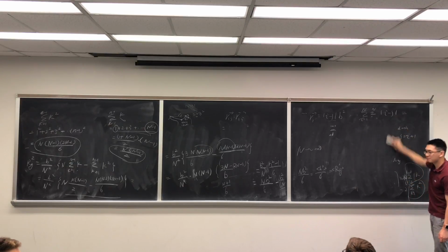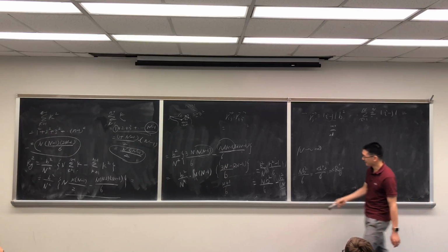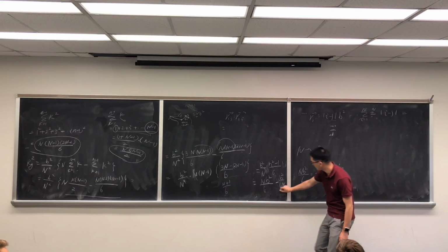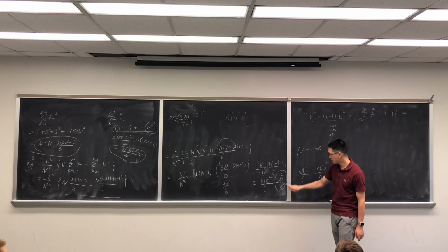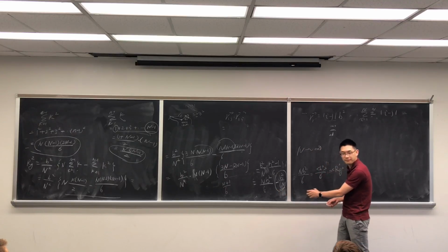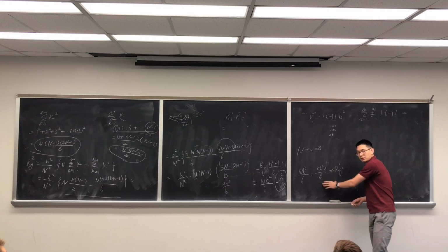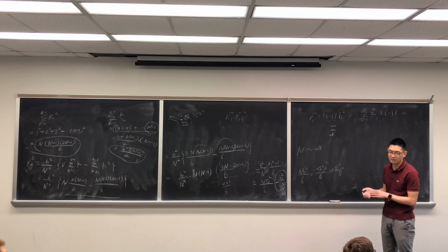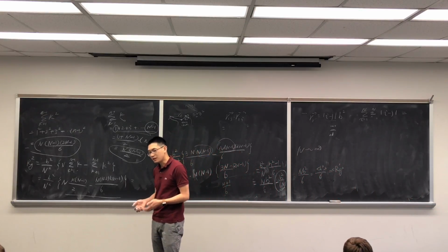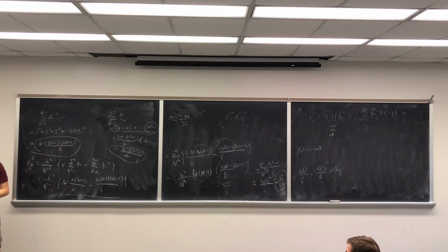So a little bit long and winding road, but it's a happy ending that you know how these mean square end-to-end distance and Rg square are linked. And we actually take one approximation: we eliminated this minus b squared divided by 6n term. And if you don't have this term, then Rg can be directly linked to end-to-end distance. Okay? That's where all the math is coming from. And I hope I explained the rationale for why we started off using that fancy triangle relationship and how we counted everything together to link these two.